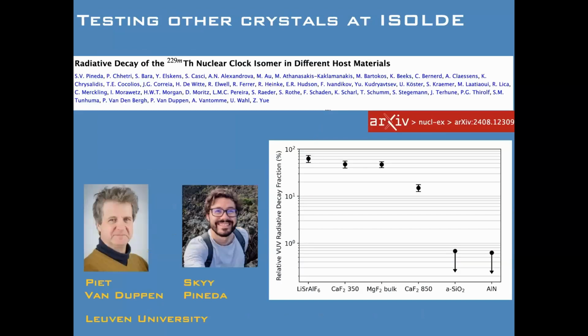So we're doing a couple of things. One is we're being really nice to Piet, and he can take crystals, put them in his beamline, and basically we can see if we see a signal from them, some fluorescence from the nuclear transition. And if we do, that's probably going to work. That's kind of like our test right now. We put things in that we know shouldn't work, and we have chemistry reasons why, and they don't work. So we're slowly building up some design principles here.